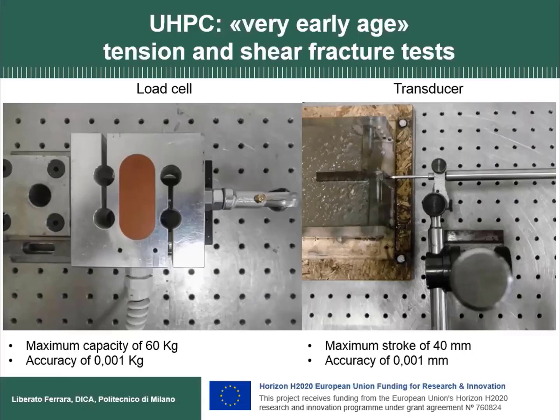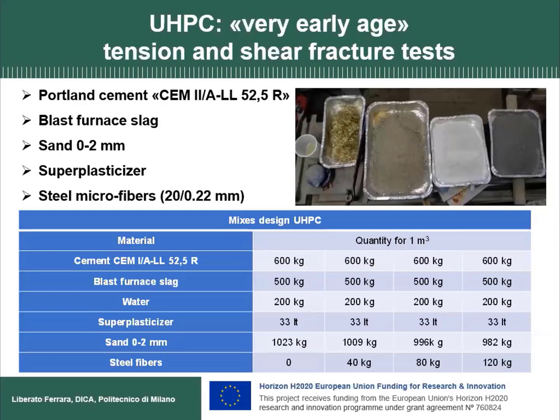We use the usual LVDTs that we use for our hardened state fracture tests because we deemed that the accuracy was correct. So we worked with a UHPC mix we have been validating for quite some time, containing CEM I. Sorry, in the writing there is a misprint. The correct notation is in the table below: CEM I 52.5 R, according to the European standard notation, blast furnace slag, a water binder ratio equal to 0.18, compensated by quite a high superplasticizer, and natural sand up to 2 millimeters maximum aggregate size.